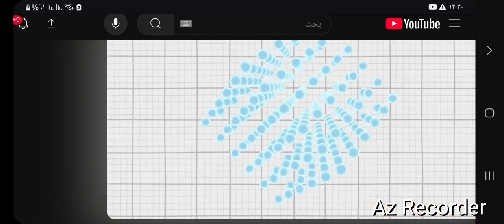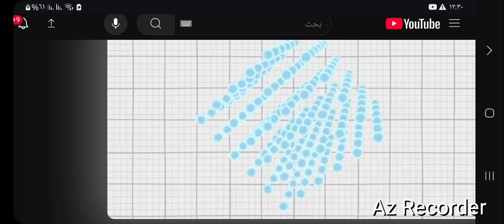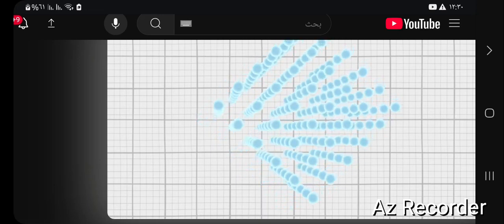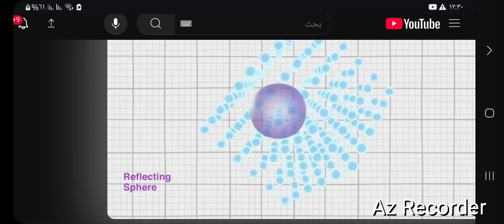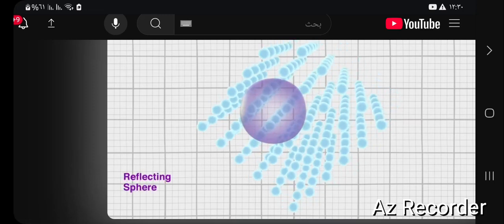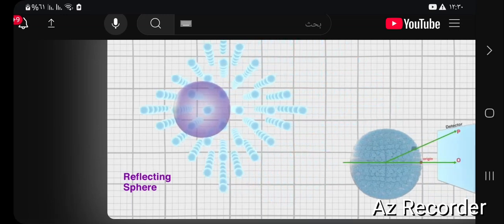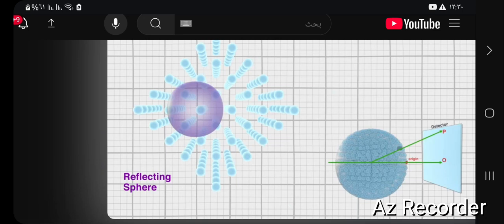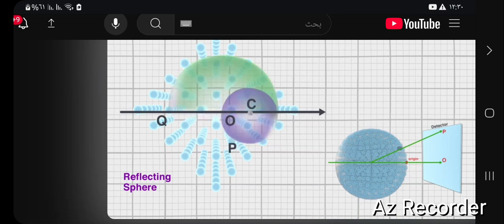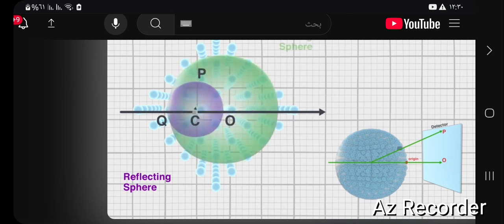Assume your crystal is a collection of atoms evenly spaced. The reflections from it would also be a collection of points in the reciprocal space. Let's draw an Ewald sphere on it. The Ewald construction is really useful in understanding how to collect data and what reflections are accessible at that wavelength. If we rotate the reflecting sphere around point O, which is the same as rotating our crystal, we can draw another sphere. This second sphere is the limiting sphere.